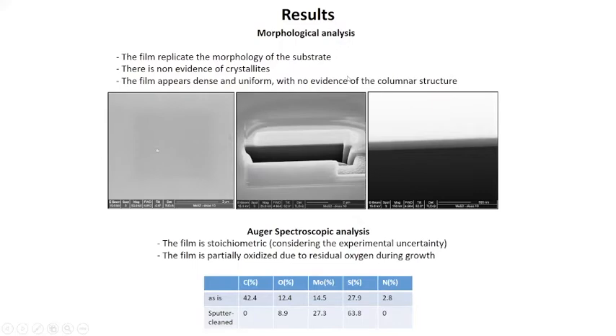Here you can see the appearance of the coating that we have made. In the top view, you can see that there is no evidence of the needle-like structures, and this is evident from the top, but also from the cross section. There is no evidence of the columns, and so more or less we are in the so-called equiaxed zone.